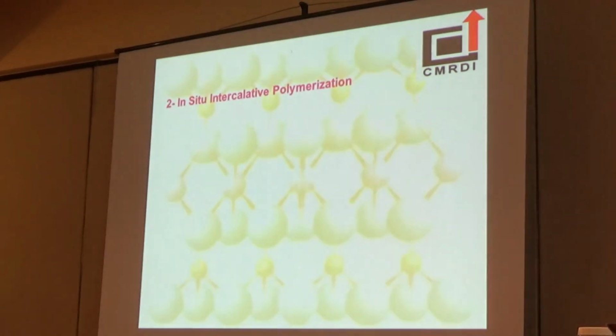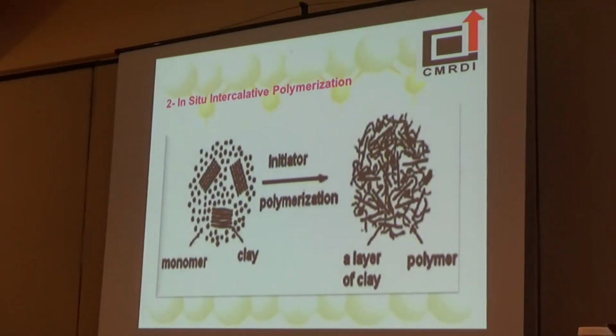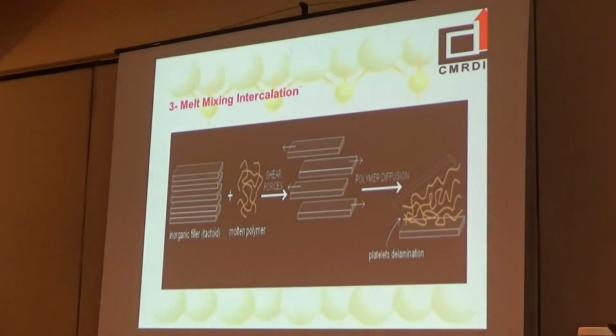The second method is in situ intercalative polymerization, in which layered silicate is dispersed in the monomer solution, and by adding the initiator, the polymerization process takes place between the clay layers, leading to the formation of a polymer layered silicate nanostructure. Finally, melt mixing intercalation, which is the most favorable method, and it is the most used method in industry, in which layered silicate is mixed with the polymer in its molten state, and then by extrusion or by applying a shear force, these layers are separated from each other, allowing the polymer to diffuse between them and forming polymer layered silicate structure.